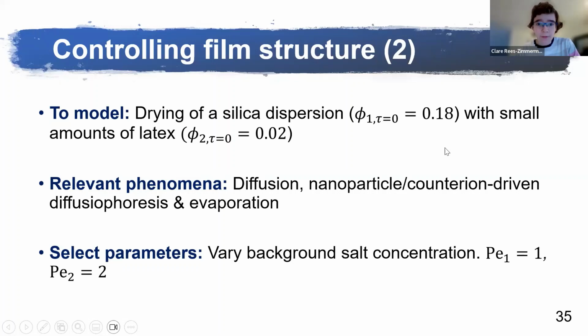I'm going to show you an example for a silica dispersion containing small amounts of latex, which would be similar to the experimental system that I showed earlier. I want to see what happens as we dry. We want to predict what might happen as we dry this. I consider what the relevant phenomena are. So diffusion, and from the experiment, we think nanoparticle and counter-ion driven diffusiophoresis as likely the most important other phenomena occurring, and evaporation. I select some parameters. I'm going to vary the background salt concentration, since the experiment showed that varying background salt concentration can tune the strength of electrolyte-driven diffusiophoresis. And I picked a Peclet number of order 1, so diffusion and evaporation are similarly important.